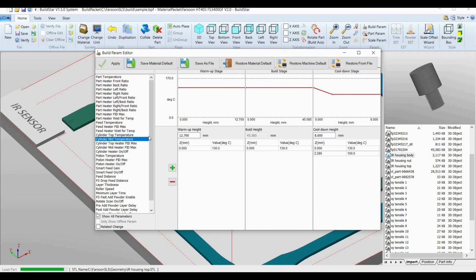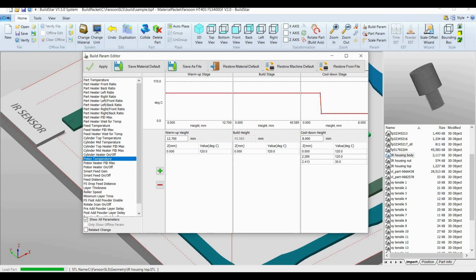If the part cake is very hard, to the point where you need more than just your hand to break apart the material, then I would suggest lowering it by 5 degrees to start out with. Also, concerning cylinder temperatures, if you are getting builds where the material is too soft on the outer edges and you have parts that have warped, you can go ahead and increase the cylinder top and mid temperatures anywhere from 3 to 5 degrees, and that should solve the problem.